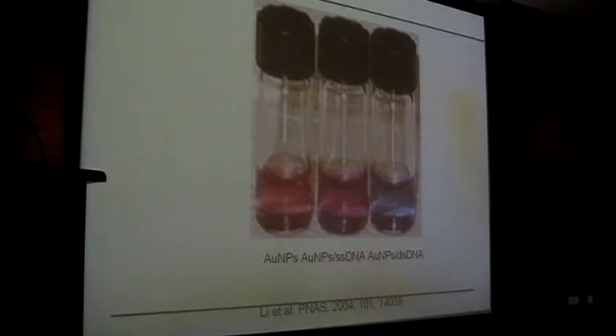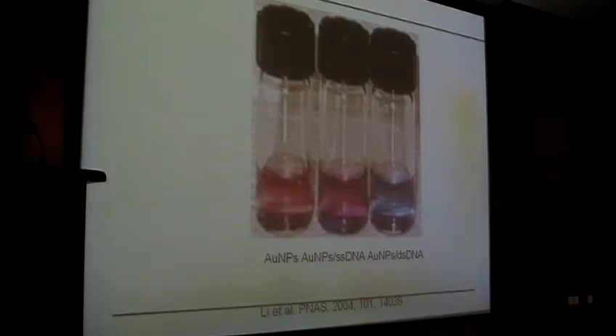Based on this interesting interaction, one may be able to detect DNA molecules. If we add a single-stranded DNA probe to a solution of gold nanoparticles, it's still red — the color changes only a little bit. But if there is a DNA target, it hybridizes with the single-stranded DNA to form a rigid double-stranded structure, and then the color changes to blue because gold nanoparticles can be aggregated by sodium chloride.